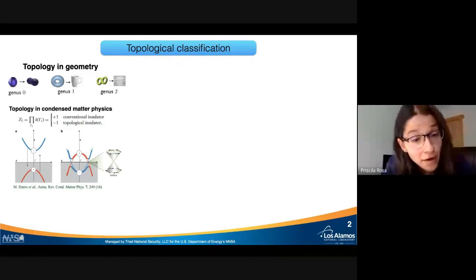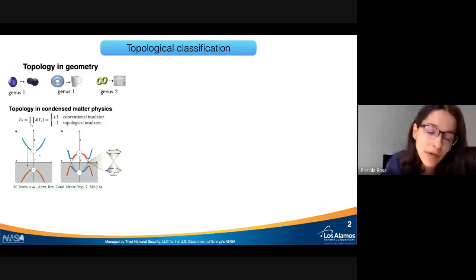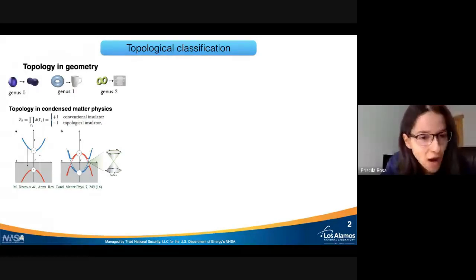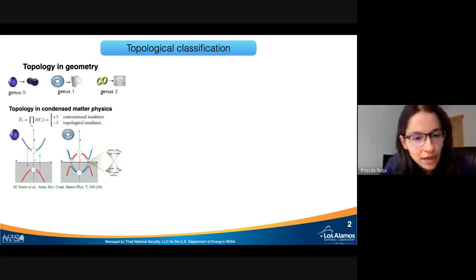You take the parity at each of the high symmetry points in the Brillouin zone, and you take the product of these parities. If the product is +1, you have here on the left a conventional insulator, just a band insulator. But if you have band inversion due to spin-orbit coupling, then your Z2 index is -1, and you have a topological insulator. Because the bulk of the material is topological, and there is an interface with vacuum or with air, we must have a surface state which closes the gap and is metallic at the interface. So here it would be the difference between the sphere and the donut.